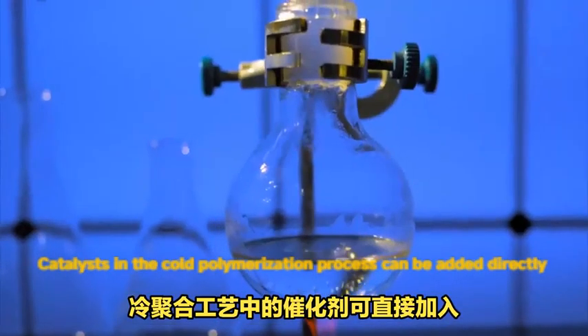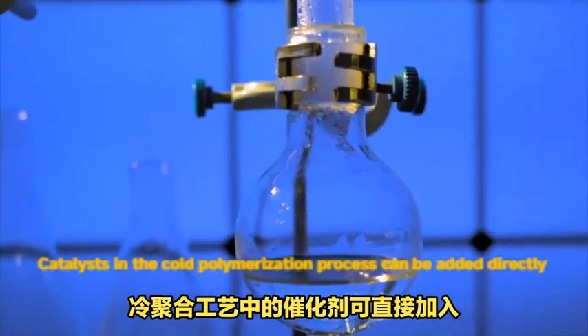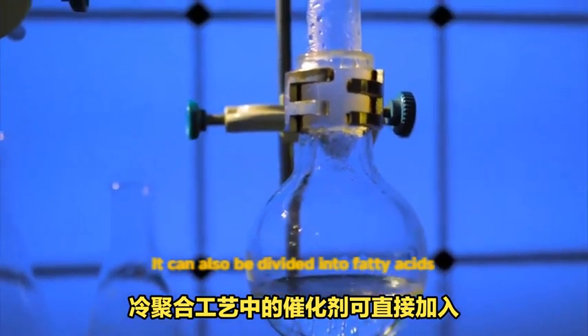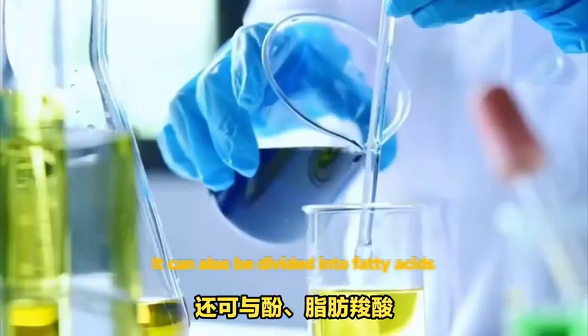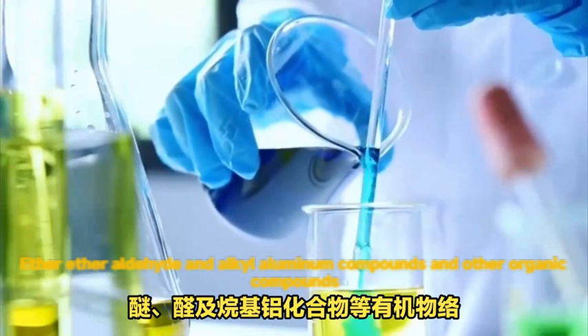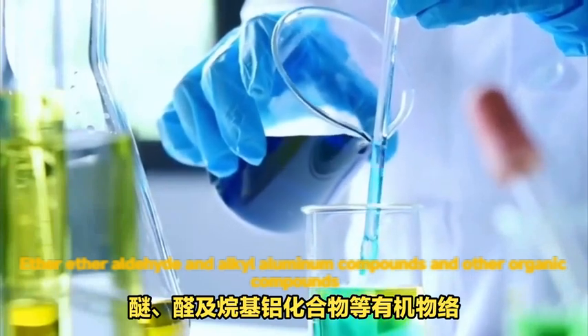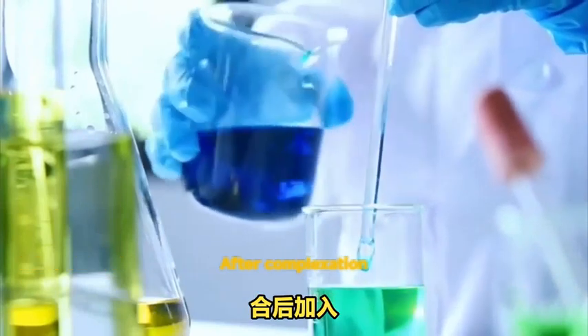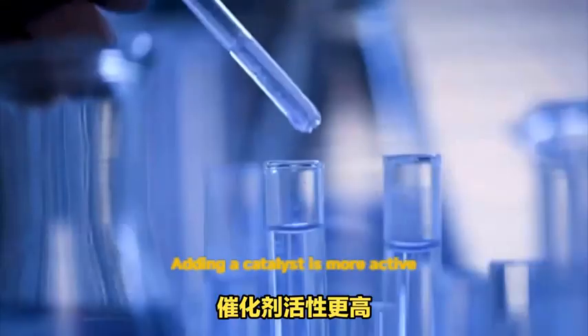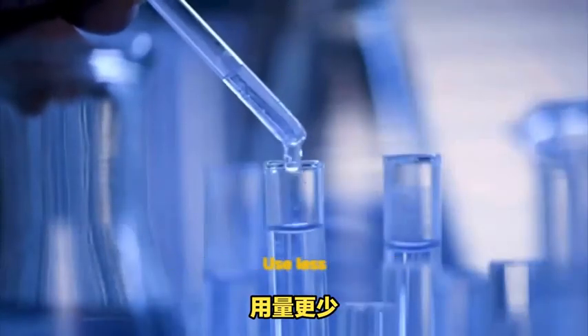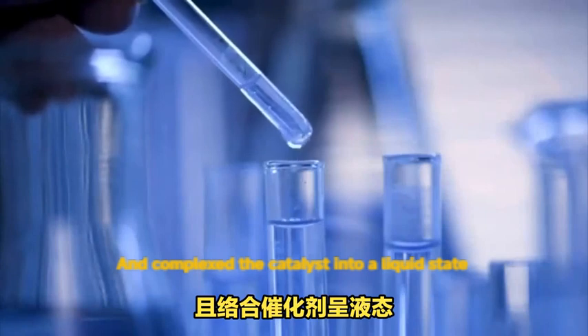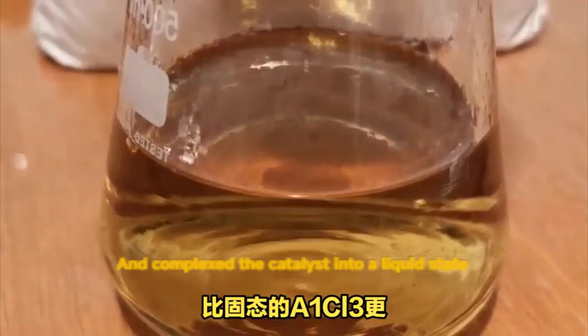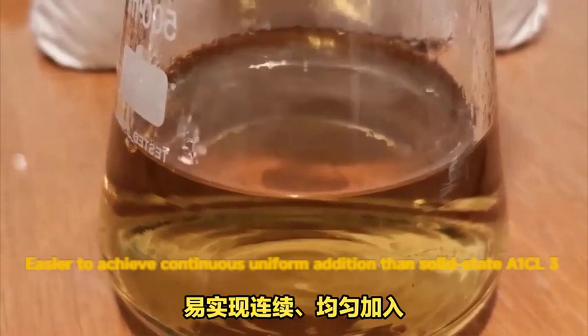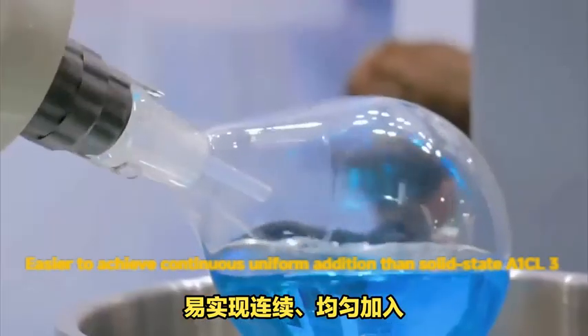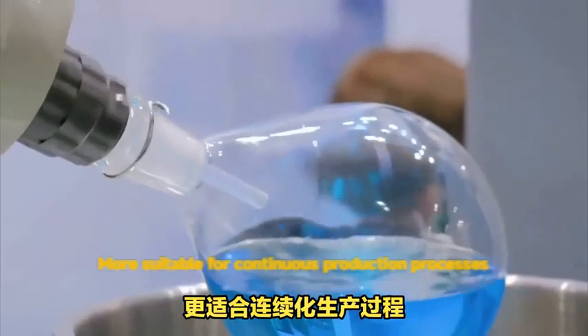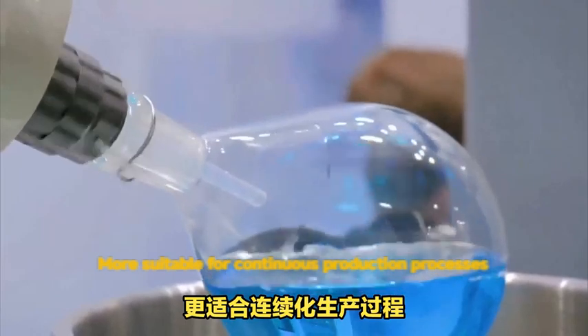Catalysts in the cold polymerization process can be added directly. They can also be complexed with fatty acids, ethers, aldehydes, alkyl aluminum compounds, and other organic compounds. After complexation, the catalyst is more active and less is used, and the complexed catalyst is in a liquid state, which makes continuous uniform addition easier than with solid AlCl3, and is more suitable for continuous production processes.